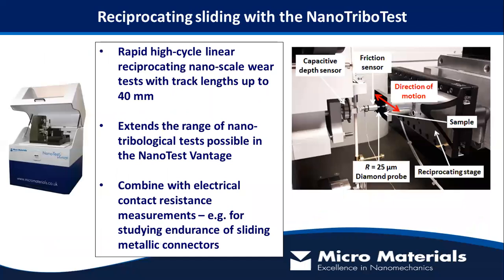So we've been involved in single asperity contacts for some time because these are possible in our NanoTest Vantage system, which is a nanomechanical and nano tribological test platform. And we've added a new module into this, which we've called the nano tribo test, which allows us to do rapid high cycle linear reciprocating nanoscale wear tests, either with very short wear tracks or right up to 40 millimeters. And these tests can be combined with electrical contact resistance measurements when we use conductive probes. And therefore we can study the electrical endurance of sliding metallic connector materials.